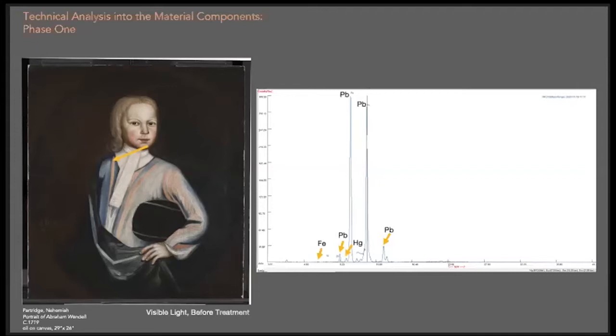In the painting shown here of Abraham Wendell, we have identified the presence of lead, mercury, and iron. Based on this information, it is likely that lead white was used in the upper layers of paint to create a highlight, the mercury-containing pigment vermilion was used to create the shade of pink, and iron likely indicates an ochre or other earth tone pigments in the ground.